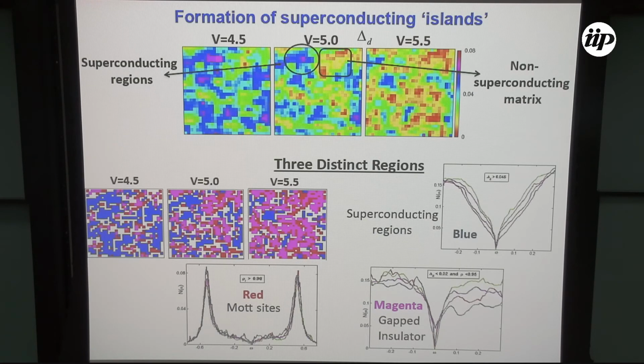You might say that this is very similar to what we saw in the IMT, but it is not. Because what is happening now is that you have two kinds of sites in this non-superconducting matrix. So the system can be broken into three kinds of sites. The blue sites are the superconducting sites, the regions or islands of superconductivity. They are separated by regions which are non-superconducting, which comprise two things. One is these red dots, which are the Mott sites, where you have a Mott insulator. And even the surroundings of the Mott insulator would be an Anderson insulator and not a Mott insulator, but still they will kill superconductivity. So there would be this whole insulating patch comprising two kinds of insulator, Mott and Anderson. Earlier we only had Anderson insulators.